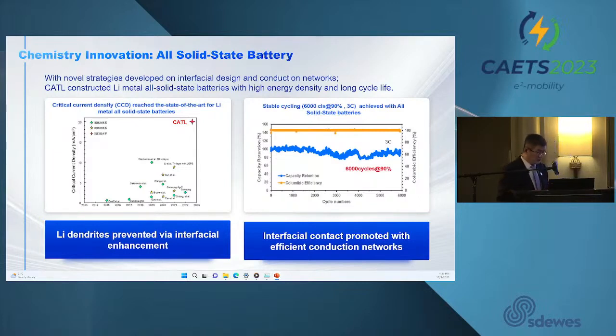An additional challenge is improving the solid-to-solid contact. Because in all solid, on the cathode side, the cathode material particle shrinks when discharging. The solid electrolyte and the particle interface may separate, and then the impedance will be very high. It cannot be used. So the solid-to-solid interface is very important. For this, CATL has developed a mixed conduction network technology, greatly enhancing the cycling stability of the solid-to-solid interface, achieving over 6,000 cycles under 3C conditions. Still, this is just in our laboratory, not in mass production. To mass production, I think it will take some time.